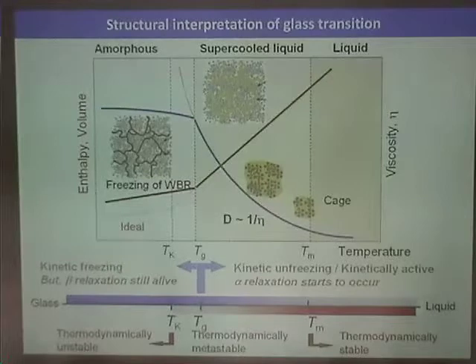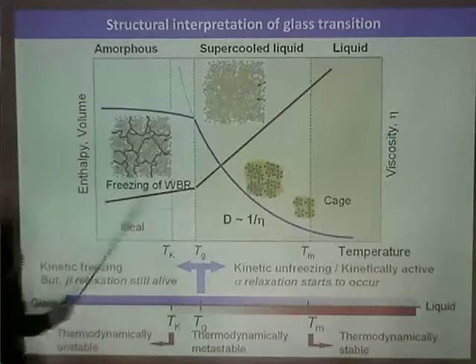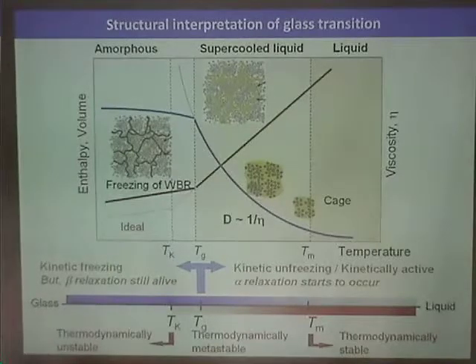Well, you're saying aging, but what happens to the flow rate in an experiment like that? It becomes constant after the experimental time scale. Right up below TG. If you go too low, it becomes only homogeneous. So below the glass transition temperature, no significant change occurs. Therefore, some part of the percolated regions remains in the glass.